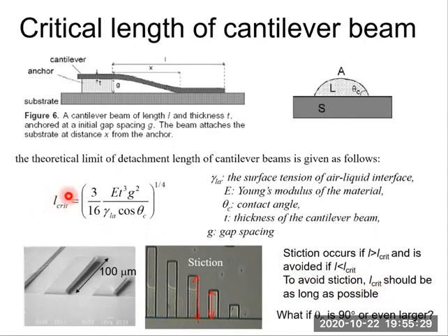So how do we increase L critical? From this equation, we can see that we can choose a rigid material, a material whose Young's modulus is large, or we can increase the thickness as T cubed. So it's fairly sensitive to the thickness. Or we can increase the gap G between the cantilever and the substrate. Oh, I forgot to mention this. In this formula of critical length, we also see theta C. Theta C is a contact angle. That's a contact angle. This angle.